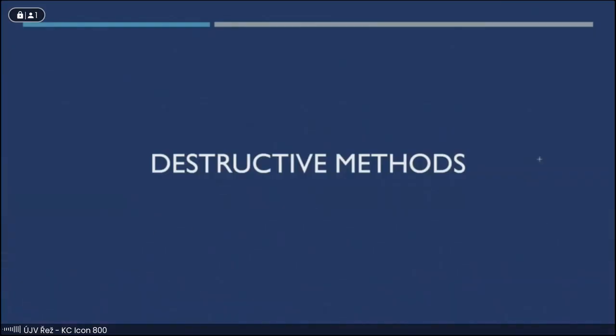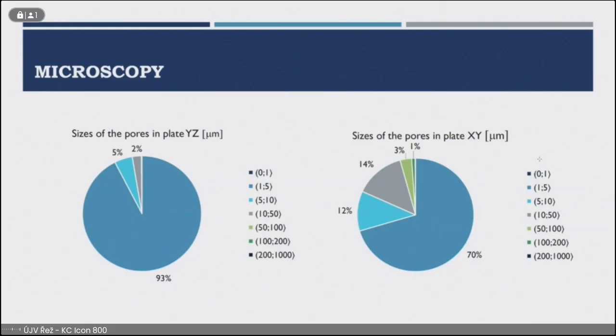Now I'd like to talk about destructive methods and their results. As I already mentioned, we used only light optical microscopy, and microscopy is considered a destructive method because observation requires special preparation of the surface of the sample. Commonly, samples are cut into tiny parts, and these tiny parts are observed. In our case, all 3 samples were cut into tiny samples, and these plates were observed.